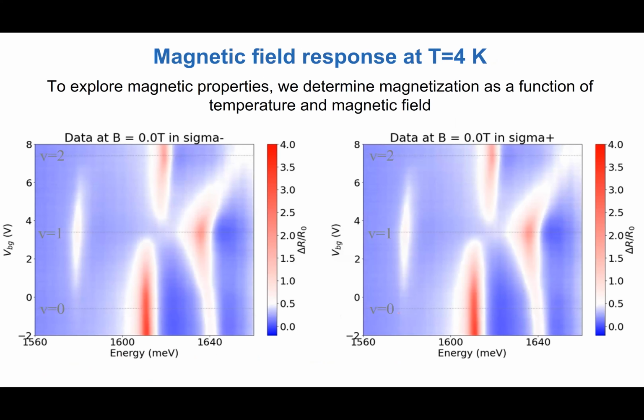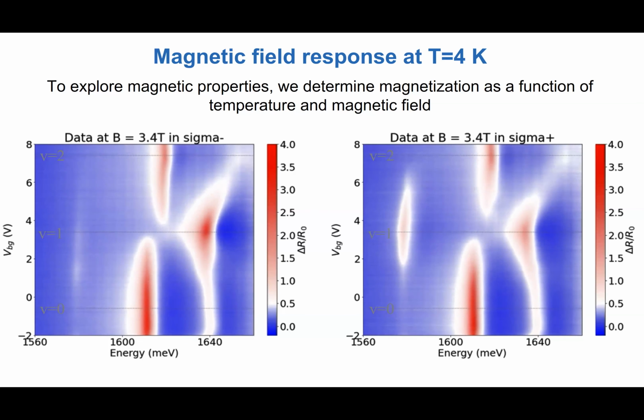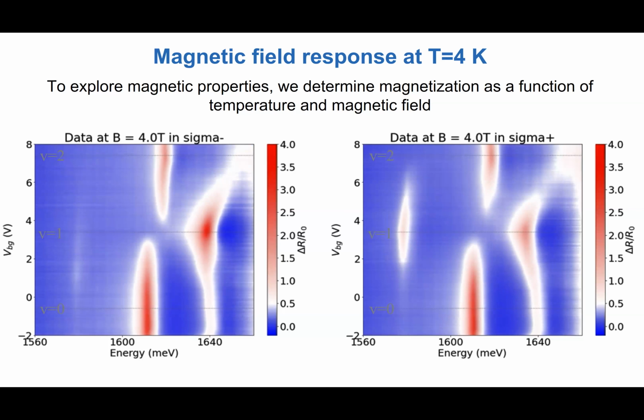What we want to see is how this attractive polaron resonance changes with magnetic field. That will tell us if it is a true attractive polaron resonance. Whereas an exciton resonance, if I apply a magnetic field, should just split by a g factor of four. So let's see what happens as I turn on the magnetic field. You see that the excitonic resonances are basically hard to see, but this resonance has now lost its weight in sigma minus, and it's almost predominant in sigma plus. So that basically tells us that this is an attractive polaron resonance.